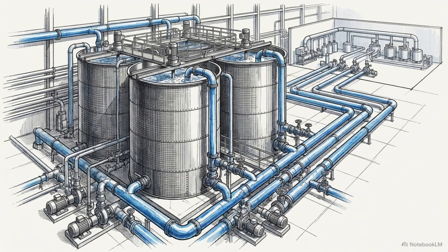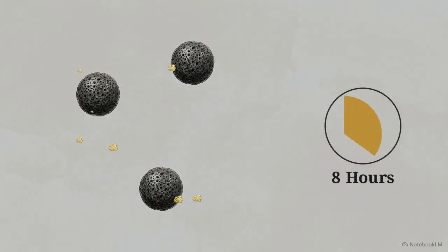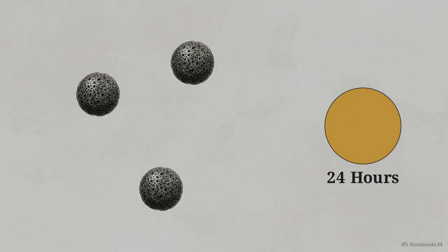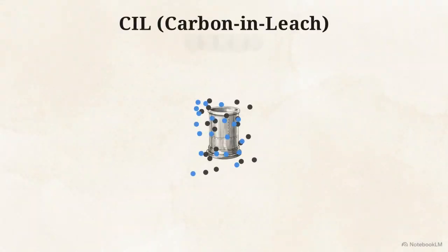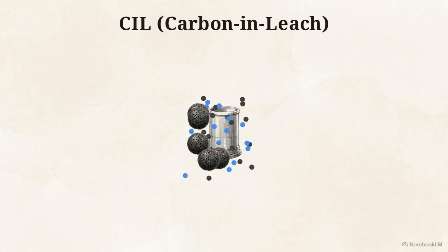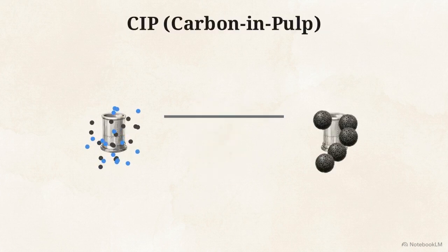Now that the gold is completely dissolved into a liquid complex, the logistics shift. The operators must physically isolate this high-value liquid from the thousands of tons of surrounding waste slurry. Activated carbon acts like a sponge, absorbing dissolved gold over an 8 to 24-hour cycle. Plants use two layouts. Adding carbon directly into active leaching tanks is a carbon-in-leach, or CIL setup. Isolating stages into separate carbon tanks is a carbon-in-pulp, or CIP configuration.